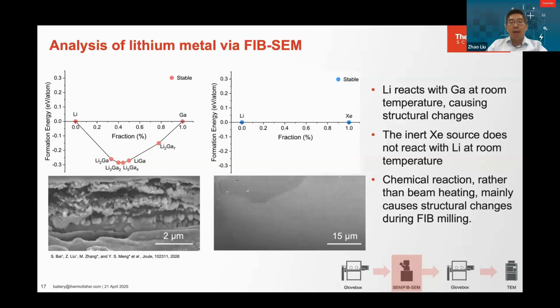So instead of using gallium at room temperature, we can use a plasma FIB, which has an inert source, for example xenon, to polish the sample. As you can see, in this case we do not see any reactivity between the lithium and xenon, and the heat damage is not sufficient to ruin the surface. That indicates that the chemical reactions are the major factor impacting the structural changes during 2D characterization. We recommend that if you only care about 2D cross-section analysis using the PFIB as a tool, room temperature characterization is enough to get an accurate result.